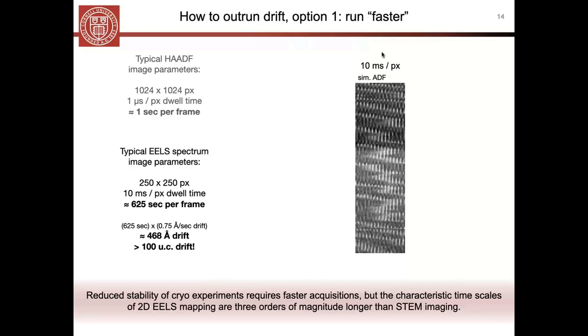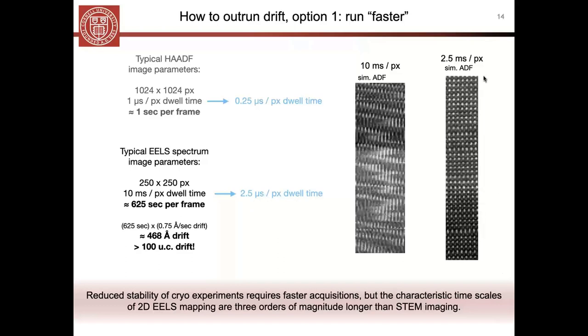But I told you that for high resolution STEM, we do already bump those dwell times down even faster. And so in my own work, compared to room temperature down to cryo conditions, I typically drop my dwell time to at least 1/4, going down for something like cryo STEM. And so you can apply that same strategy to your EELS map. So if you actually drop this 10 milliseconds dwell time down to, sorry, this would be 2.5 milliseconds dwell time, you're going to get an ADF image that looks something like this, again, also under cryogenic conditions.